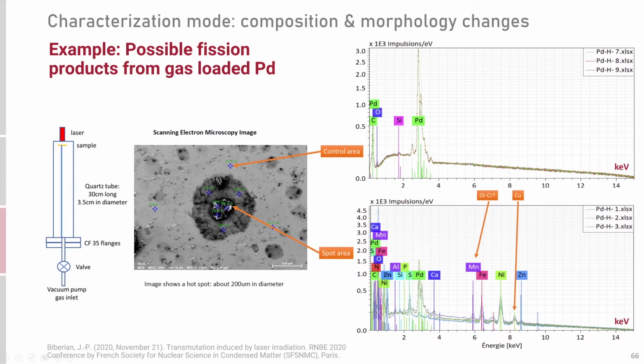In this experiment, a palladium thin film is irradiated by a laser in a pressurized deuterium atmosphere. After several weeks, a visible change can be seen at the surface of where the laser irradiated the sample. An elemental analysis suggests that the amount of palladium there has gone down, while the amount of lighter elements such as iron and zinc there has gone up.